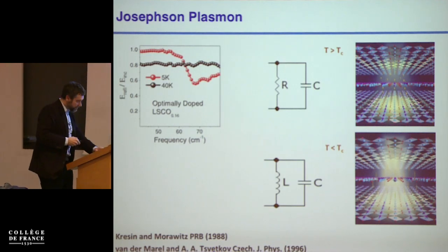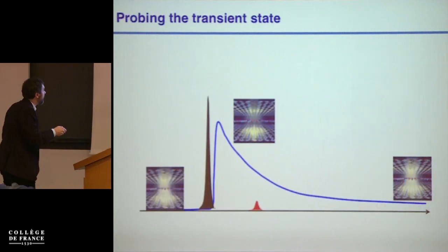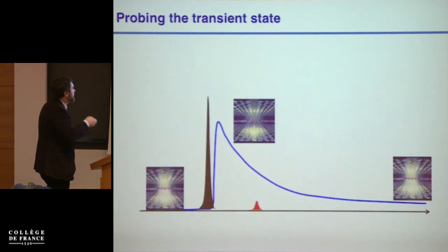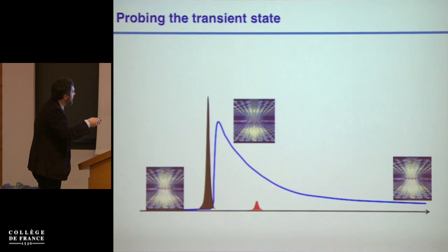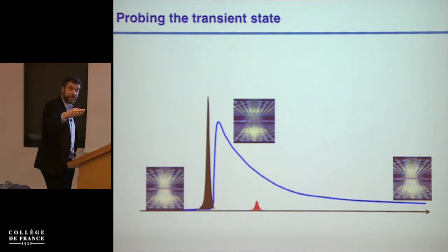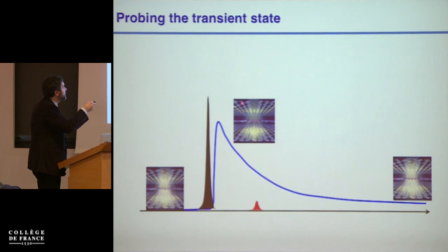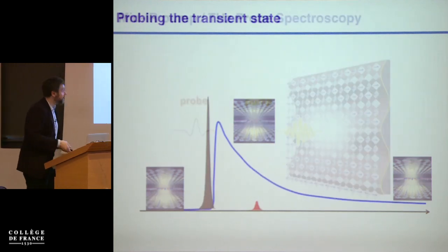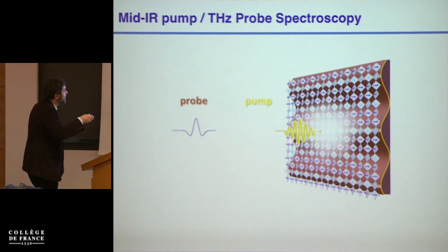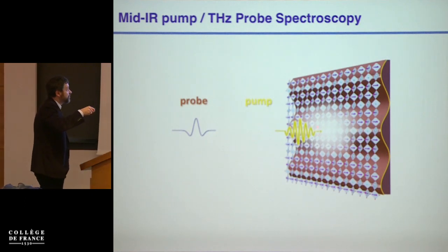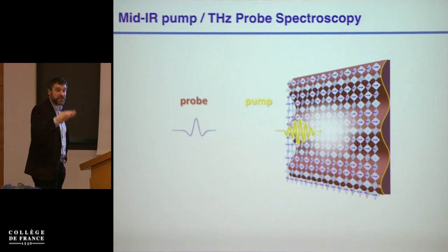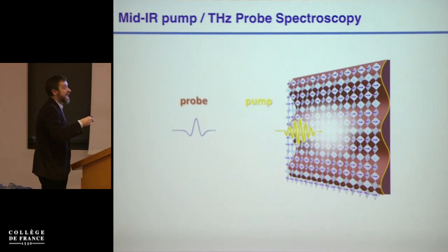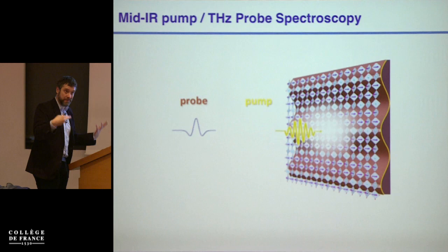Okay, so when I do my experiment now, I'm gonna start in some state, and I'm going to shake this, and then I'm going to look at this as before, as a function of pump probe time delay, and I'm going to look for features in the terahertz spectrum perpendicular to the planes that are indicative of either stronger or weaker superconductivity. Okay, so this is the experiment. I come with a vibrational pump which is resonant with the 600 wave number stretching mode in the planes. I cross my fingers and I hope to melt stripes.